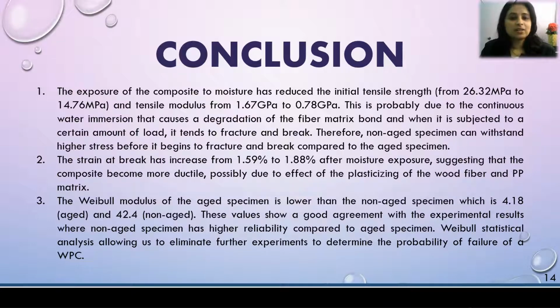And finally, the Weibull modulus of the aged specimen is lower than the non-aged specimen, which is 4.18 for aged and 42.4 for non-aged. These values show a good agreement with the experimental results where the non-aged specimen has higher reliability compared to the aged specimen. Therefore, it can be concluded that Weibull statistical analysis allows us to eliminate further experiments to determine the probability of failure of WPC.